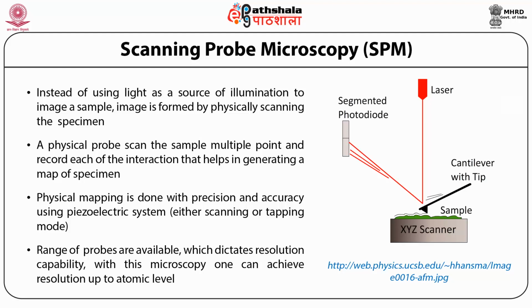For example, in this picture, as you can see, a laser is pointed toward the cantilever tip and the cantilever tip is scanning the entire sample. Depending upon the depth and height at which contact is made, that information is directed toward the photodiode, which is used to construct an image based upon the interaction pattern that the cantilever experiences. This mapping is very fine and can be very high resolution because the cantilever tip is moved using a piezoelectric system, whether in scanning or tapping mode. In both processes, the mapping is highly motorized and highly controlled.